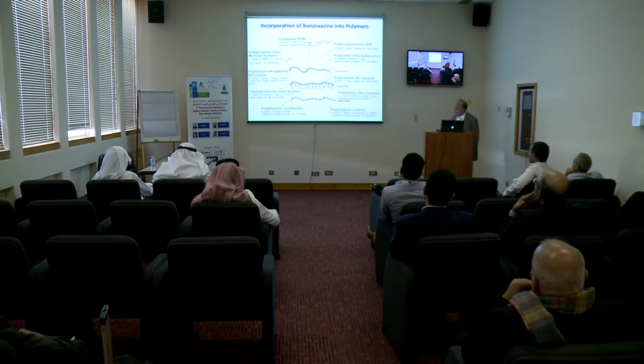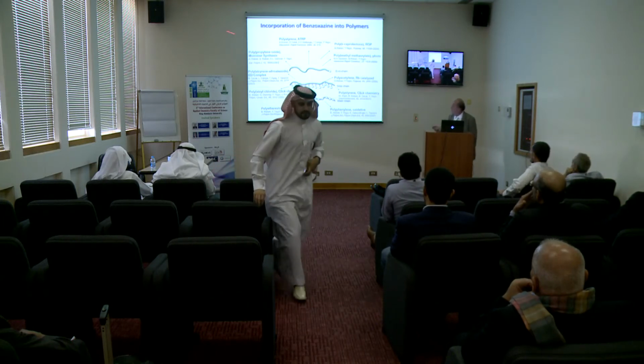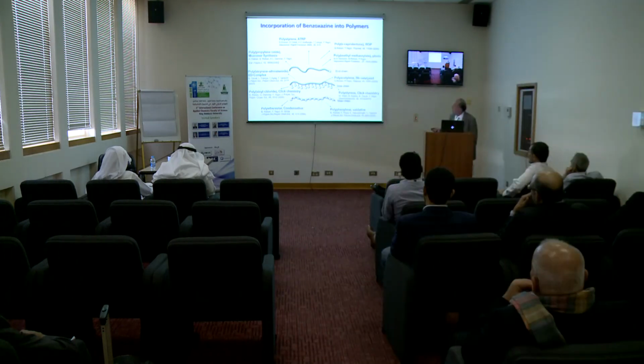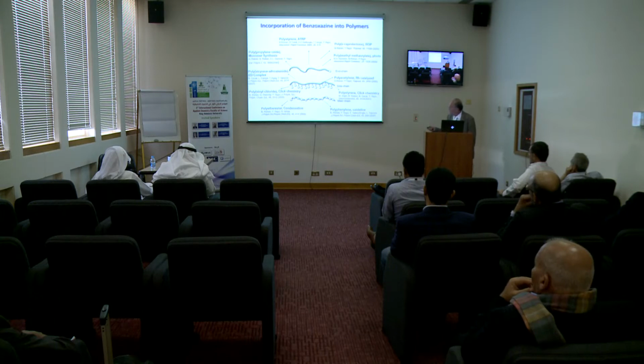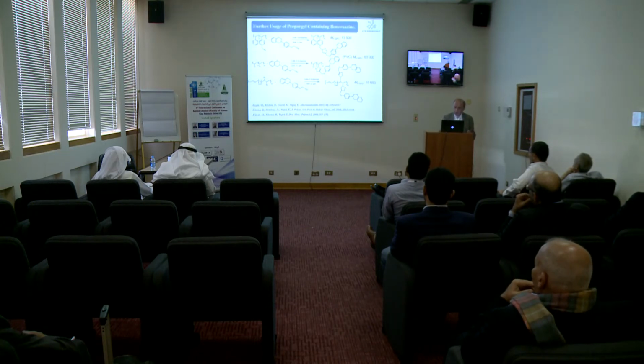But they have some disadvantages. They are brittle, weak film-forming properties, low processability, and so on. In order to overcome such problems, we made some strategy that you can combine with polymers. We published many papers in this area. Some of them are shown here. You can attach at the chain ends or side chains. These represent benzoxazine rings. You can process because of the polymeric nature of the main chain. When you heat these polymers, you have a cross-linked material with high thermal stability.